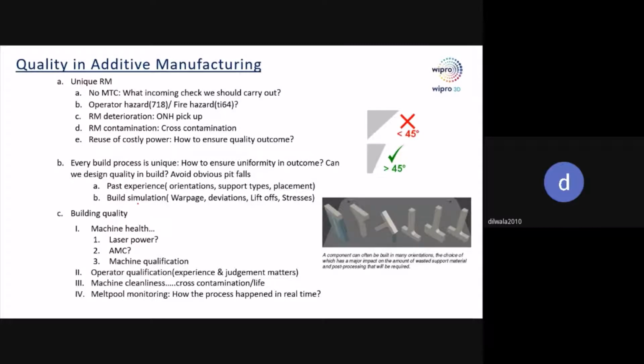Then comes build simulation. Up to an 80% confidence interval, we can predict in simulation how much distortion is expected and where stresses are more during build. We have specialized software for that. Depending on the simulation results, we can add stock or create less stock so that we will not reject the part due to more warpage or reject the part due to less stock and more warpage.